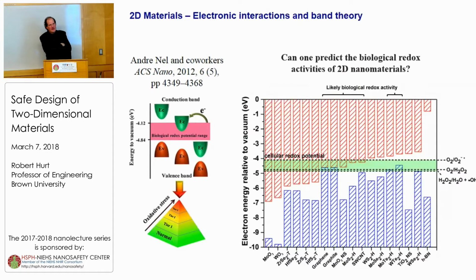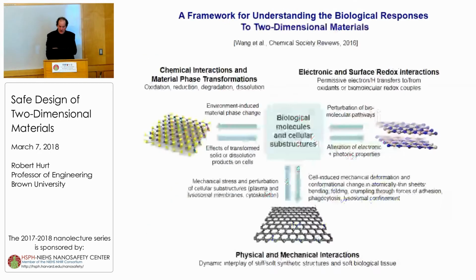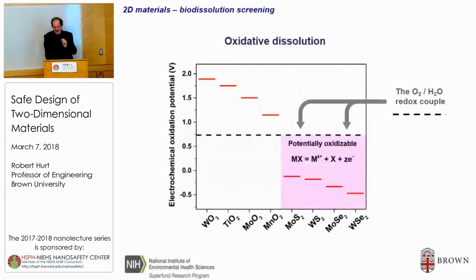Yeah, we haven't necessarily. It's a good question. We haven't necessarily tried to correlate the oxidation activity using this theory. This theory has more to do with whether electrons can go in and out associated with these biological redox couples. So there's some relation that you're getting at, certainly. But the theory we've been using for oxidation is this one, really, which is actually not based on the band gap, because for the bulk materials at least, you can calculate the thermodynamic potential for oxidation by writing out the stoichiometric reaction. These aren't the nanosheet versions, but it gives you that couple, so we don't directly use the band gap.